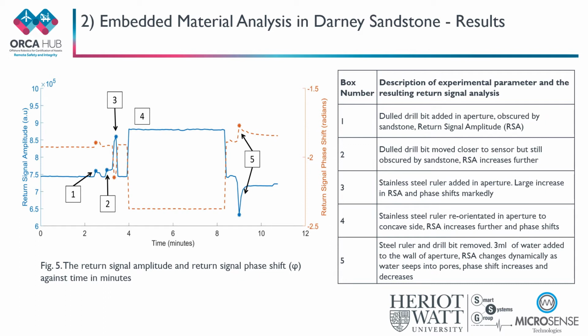As the dulled drill bit is inserted into the aperture, there is a slight shift in the return signal amplitude and phase shift as indicated at point 1. As the dulled drill bit is moved to the near side of the aperture, there is an increase in return signal amplitude at point 2. At marker 3, the stainless steel ruler is added within the aperture. There is a large increase in return signal amplitude and the phase shifts markedly also.